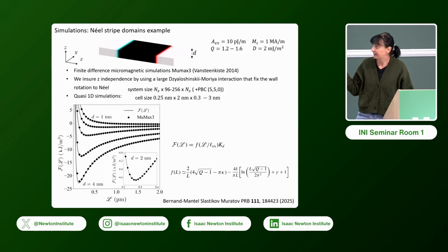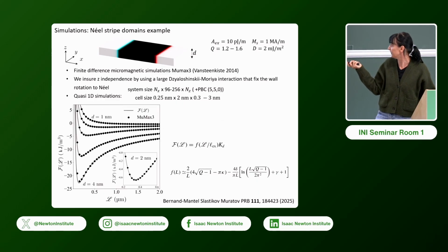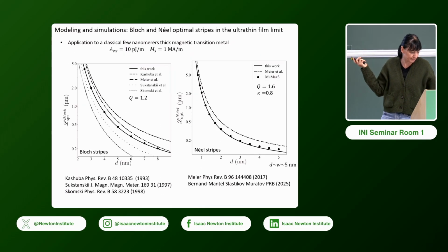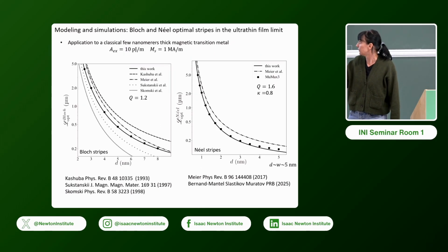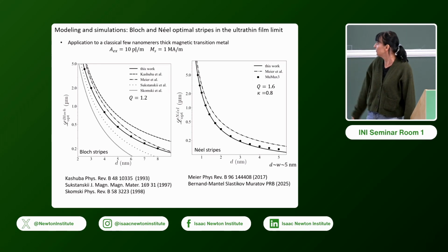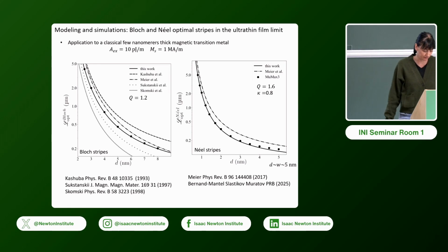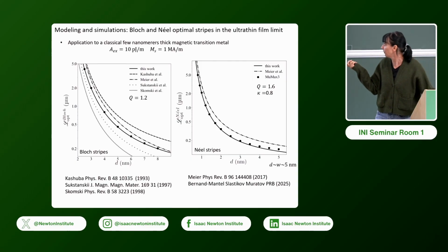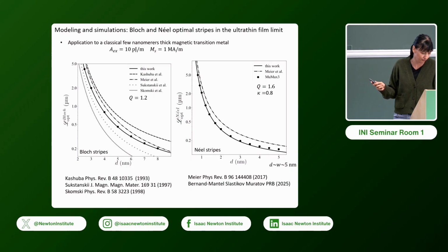So I can then vary the thickness of my simulation and follow the minimum, and at the end I get all these points corresponding to the minimum, which are of course falling into the formula that was calculated by a mathematician. So giving an answer for experimentalists that this is the formula that should be used from now on.